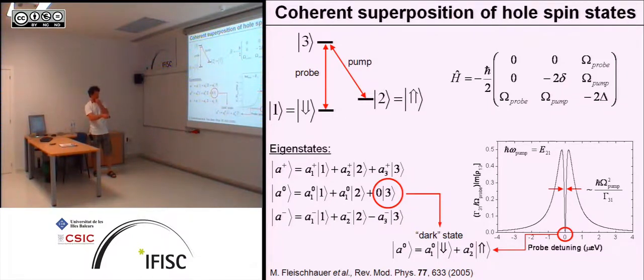And now because this state corresponds to two ground states, and we've shown that hole spins have a very long relaxation time, it is sensitive to the dephasing of the spin states against each other. Because this, in the end, is a superposition of two quantum states, and like with an optical phenomenon where you interfere two optical beams, you can only do it within the coherence length of the system. Here you can only do it in the coherence timescale of the system. So the visibility of this dip strongly depends on the coherence of state 1, or the dephasing of state 2 relative to state 1, let's say.